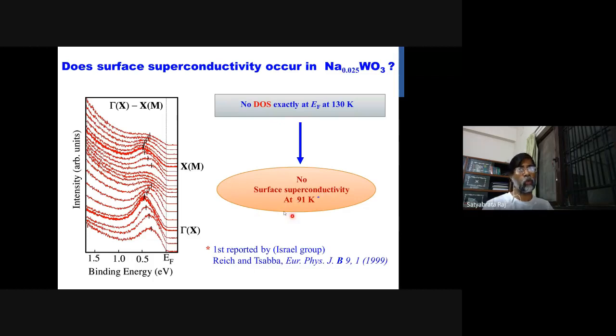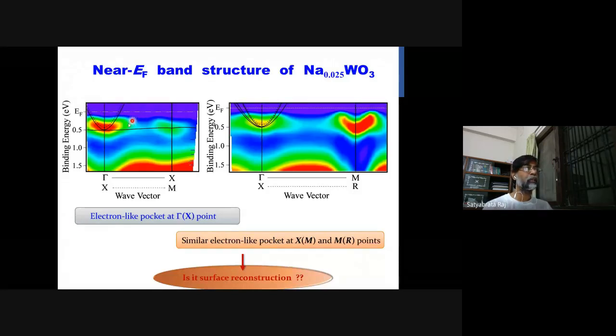So at such high temperature, we have checked the surface electronic structure and the bulk electronic structure. There is no quasi-particle feature at EF. We discard their claim. So this is your parabolic band, without the Coulomb gap, overlapping with the sodium WO3, and we have the same replica of the Fermi surface. You can see the parabolic one. This shows electron-like pockets at X and M points.